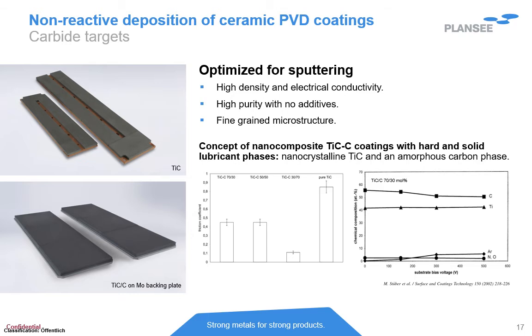In this work published by Michael Stüber, titanium carbide targets enriched with additional graphite powder were used for deposition of nanocrystalline titanium carbide particles in an amorphous carbon phase. By changing the ratio between titanium and carbon in the target itself, it was possible to deposit coatings with different values of friction coefficients. This is shown in the diagram on the left side. In the diagram on the right side, it is shown how the amount of carbon in the coating can be triggered by changing the bias for a constant target composition.